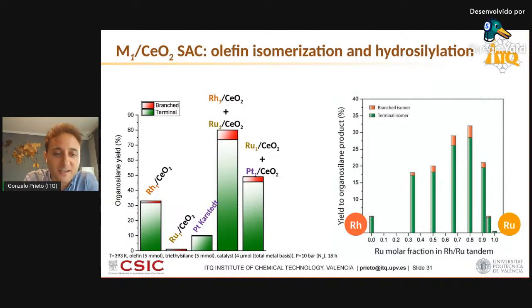And as you can see here on the left-hand side, if we combine those two single atom catalysts in one single pot, so that one is responsible for olefin double bond migration, and the other one is responsible for this regioselective hydrosilylation, they show much higher organosilane yield than either of the two separately, even than a benchmark molecular platinum Karstedt catalyst under the same conditions, or combinations of ruthenium with platinum, which is active for those two reactions. That's already a result exemplifying that decoupling the two reactions on two independent sites might be preferred to letting them compete on the same site, where the residence time of the substrate on site might be way less effective if the two reaction pathways are competing. This is the case for the platinum single atom catalyst.